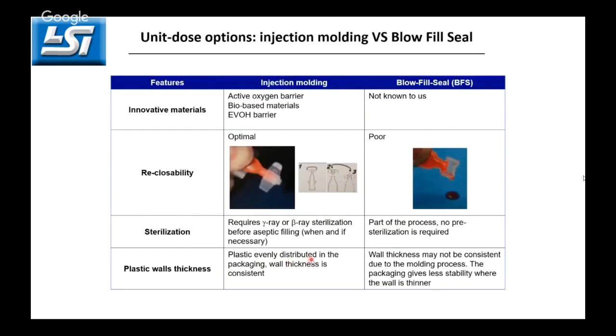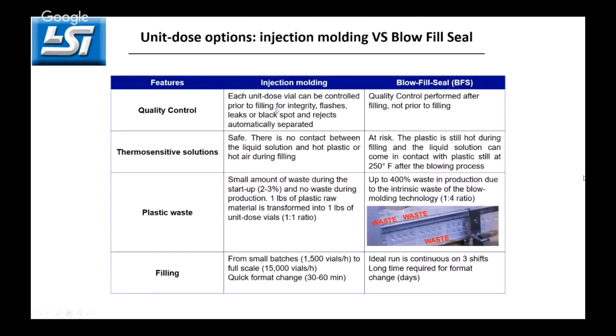The injection molding process distributes the molten plastic evenly in the whole mold with a consistent wall thickness in the plastic container. While the blow molding process does not give control of the wall thickness, with the result that the blow-fill seal container may be more prone to permeability or less stable where the plastic wall is thinner. Being a two-step process, Lameplast does an automatic 100% control of the molded vials prior to filling, checking for integrity, flashes, leaks, or black spot. A blow-fill seal vial can be controlled only once it is already filled.